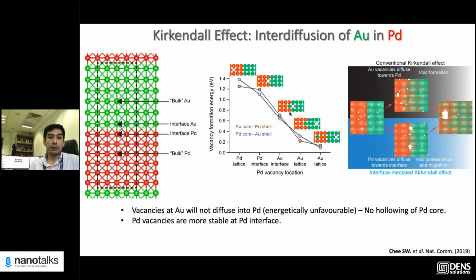And this can be understood if you just look at the calculated vacancy formation energy diagram here. Keep in mind, palladium is red and gold is green. The vacancy formation energy in bulk gold is the lowest, right? So a vacancy in gold would not want to diffuse towards palladium, even though palladium is a fast diffusing metal. The energy barrier associated with the diffusion of gold into palladium is going to be higher.